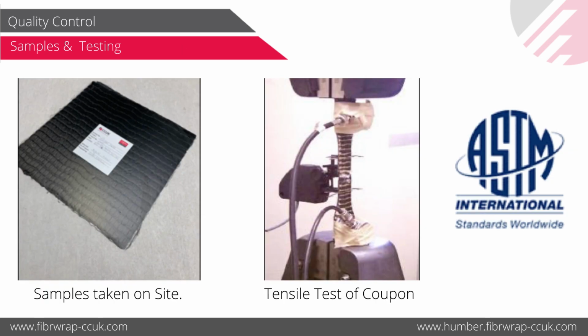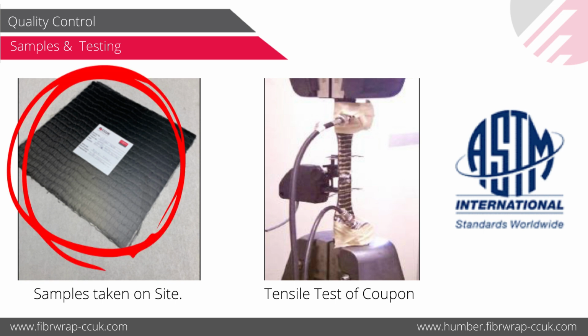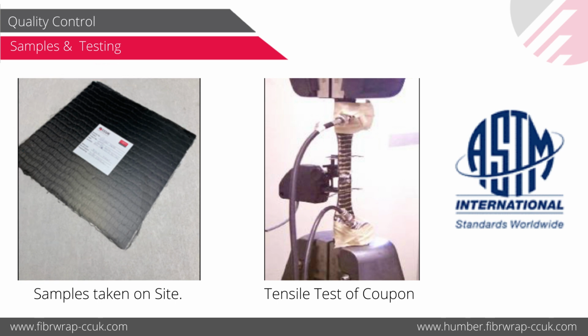And then the second test we do is basically to check the property of the material. So this is called plate testing, and it tests the composite property. So it is mixed together. When they do the saturation of the fabric, they also create these 300 millimeter by 300 millimeter plates. The current requirement as per TR55 is to cast 2 plates per day or 2 plates per roll of the fiber, whichever is higher. And they send it to an independent laboratory.